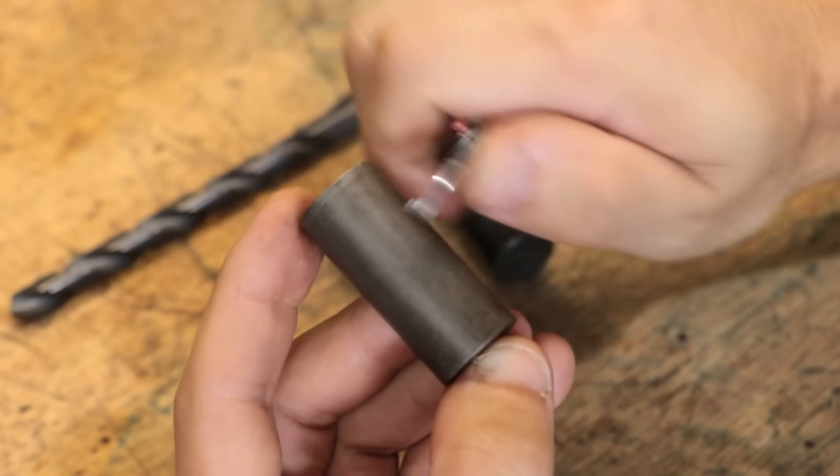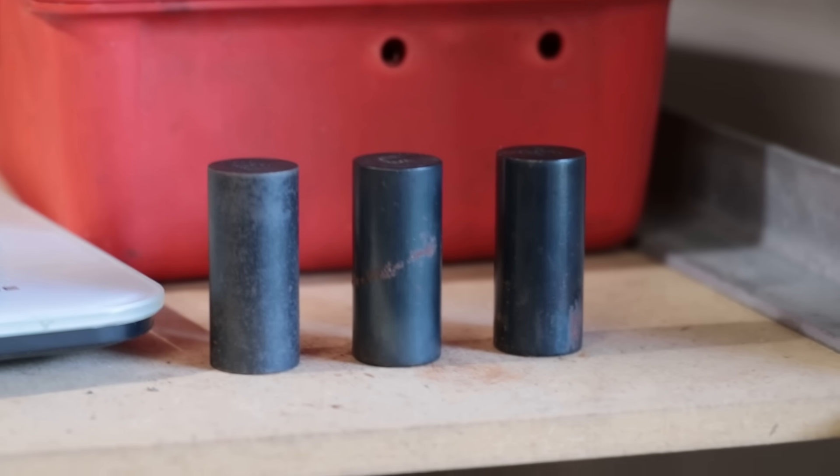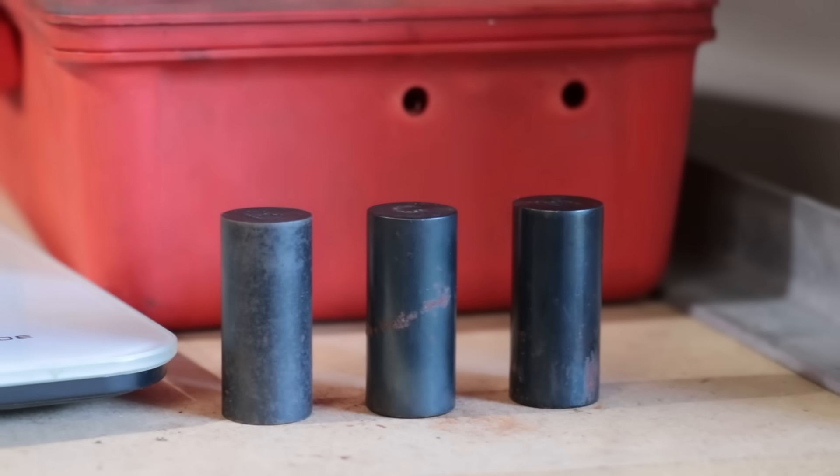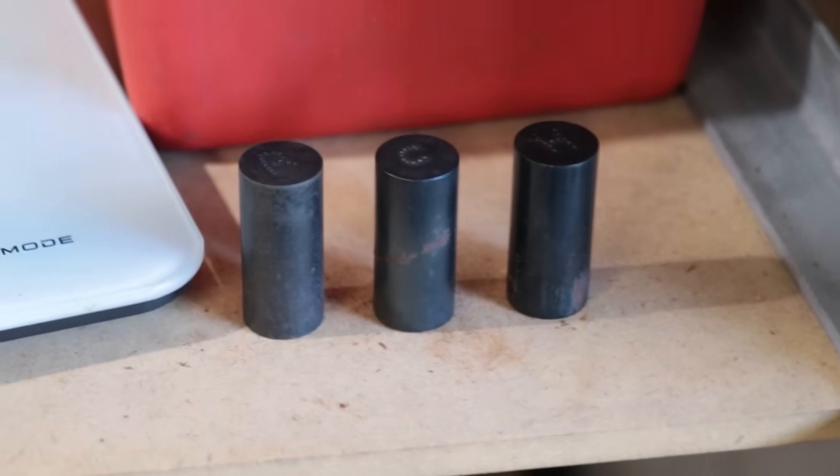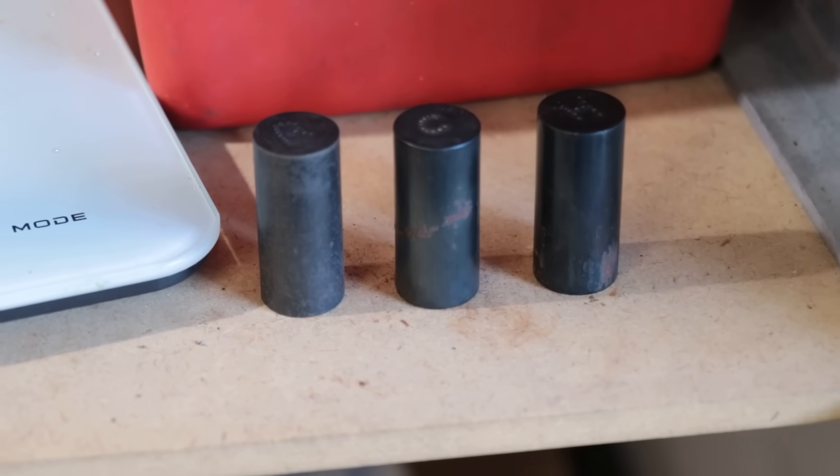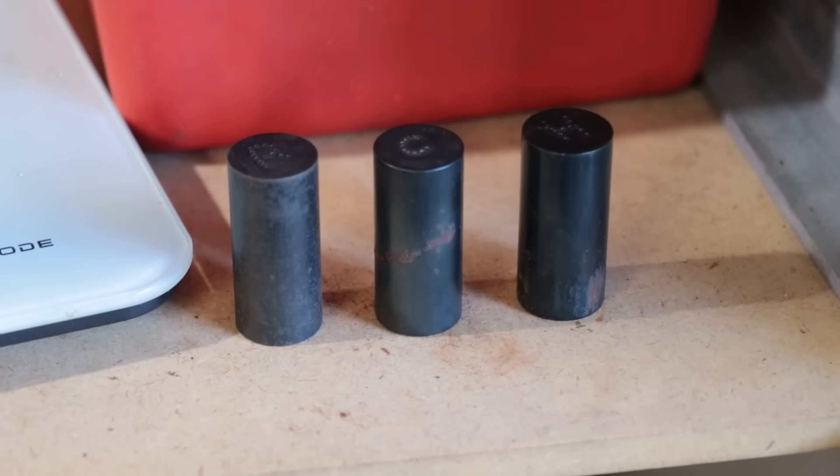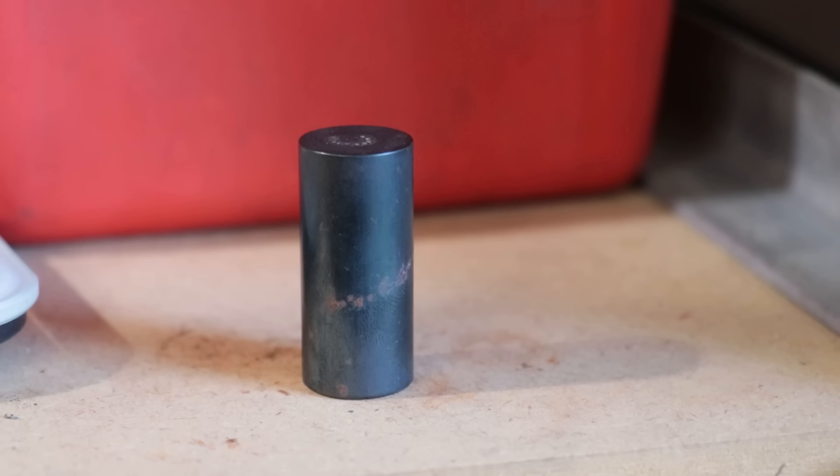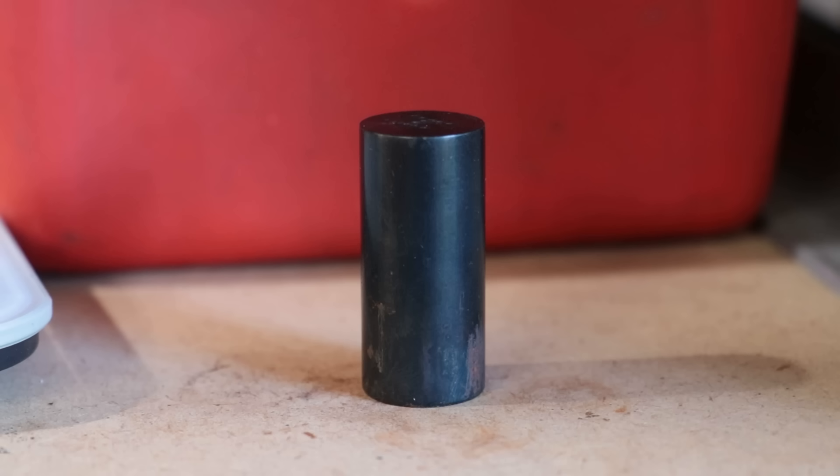Reason number two is it works pretty well at resisting corrosion. You see I've left these samples on a shelf next to the workshop door since the beginning of January, and they've all dealt with wind, rain and moisture. As you can see, the cold blue has fared the worst, but it still has done a pretty good job, but it still developed a little bit of rust.